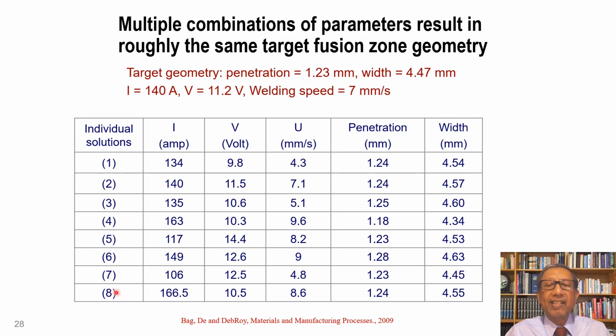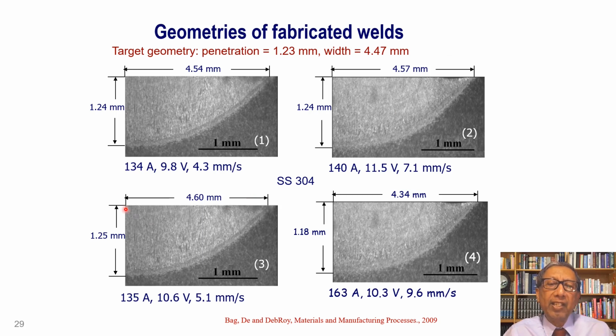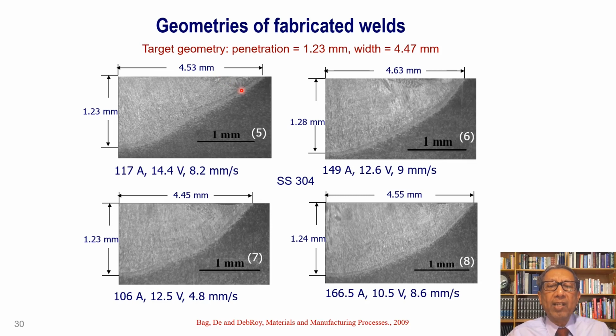We take each of these cases, we physically do an experiment, and then look at the depth and the width of the tracks and compare them with our specified values. So we did experiments using the different combinations of current, voltage, and scanning speed. And for each condition, we obtained a depth of penetration and the width of the fusion zone similar to what our target was. So all of these different combinations of variables could give us the geometry. What we computed matches with experiments. We could get the target geometry of the fusion zone via 8 different combinations of current, voltage, and scanning speed.